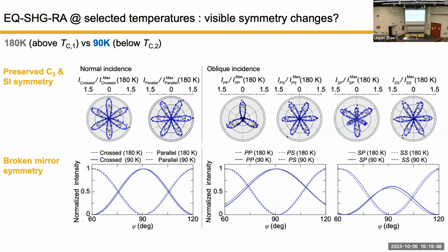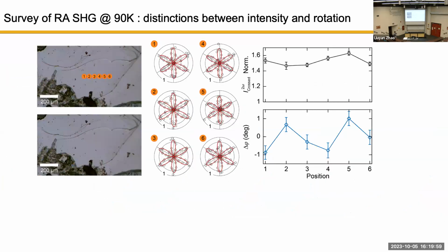So from high temperature to low temperature, 2 things happened. The intensity grew much bigger than before, but the orientation changed only a teeny tiny bit. Then we want to know, what does magnitude mean and what does orientation mean? So we survey across the sample at different points. What we see is that at low temperature, at every location, the intensity consistently increased, while the orientation of the flower pattern can be either clockwise or counterclockwise. So this tells us that the intensity and the orientation are probing different things of the state, because the intensity cannot tell the time reversal related states, while the angle orientation can.